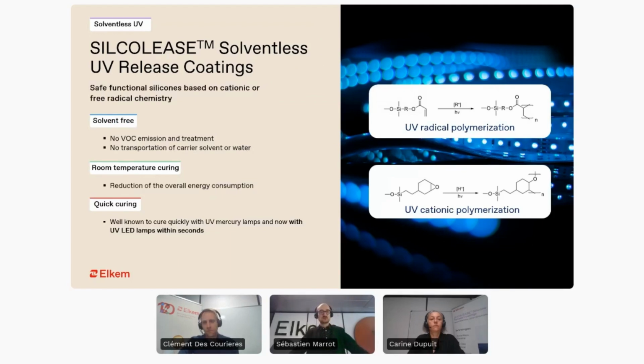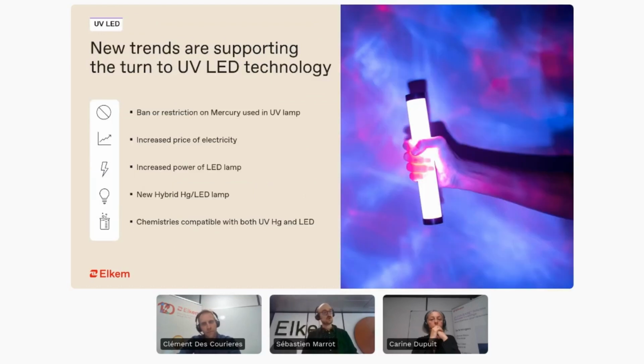SILCOLEASE solventless UV release coatings are safe functional silicones based on cationic or free radical chemistries with the following features and benefits. First, they are solventless products leading to no VOC emission and treatment, no transportation of carrier solvent or water. Then they do not need heat activation and they can cure at room temperature, leading to the reduction of the overall energy consumption, as we will see in the next slides. At last, they are well known to cure quickly with UV mercury lamps, and from now on, with UV LED lamps within seconds. Why do we strongly believe in UV LED technology?